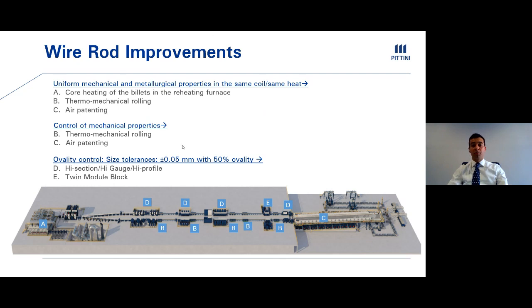In order to have uniform characteristics, we have to control the mechanical properties during the whole process. Not only the tensile strength, but also elongation properties. These are very important, for instance, in the production of PC strand and springs. Ovality control and size tolerances also have a special focus. I would like to highlight the twin module block device installed in the sizing mill for benefits in the final shape and tolerances.